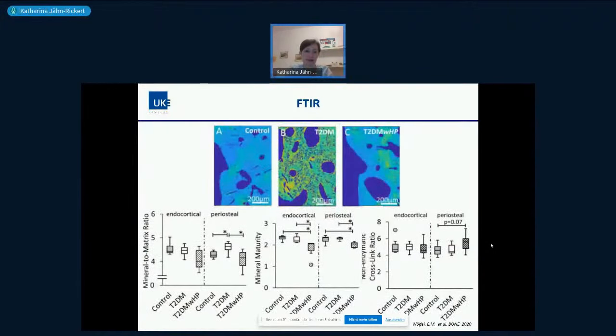But last, but not least, I would like to also mention Fourier-transformed infrared spectroscopy, because this is particularly interesting if you are looking at the quality of the collagen inside the bone matrix. Here again, the study from my colleague Eva, who looked at specimens from patients with type 2 diabetes. As I mentioned before, we had control specimens, then the group of type 2 diabetes, and then the type 2 diabetic patients that showed a higher cortical porosity. Then she quantified with this spectroscopy certain parameters. It's a spectroscopy, so there are certain peaks that one can look at that can give you information about the matrix.